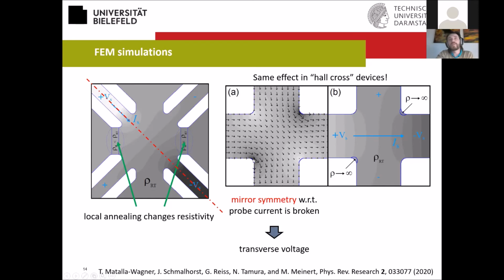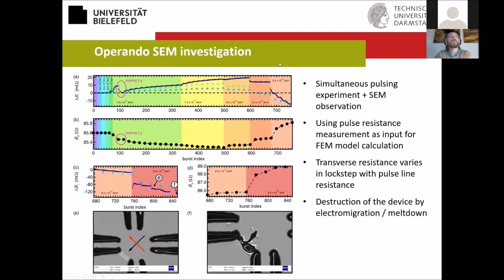So we have these hotspots here in these corners. We send the resistivity in this example to infinity, and we see again that we have this asymmetry in the voltage, which leads to these transverse signals. In addition to these experiments, we also did operando SEM investigations. So we looked at our structures in the SEM while doing the pulsing experiment, and we linked this to FEM simulations.